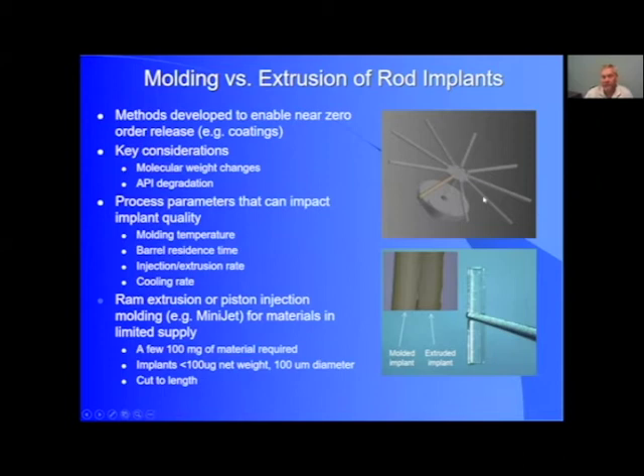So here on the illustration at the top is an example of a mold to make a bunch of rods. Basically the material is coming in, you have a disc here where the material starts to fill and form, and it flows up and to the right a little bit, and then is distributed through a small gate that's a disc, and then out into the different spokes that are rods, and these can then be broken off and either utilized at length or cut to final length, versus an extrusion where it would just be continuous and then cut either in line or offline.